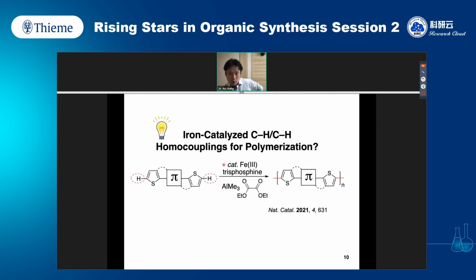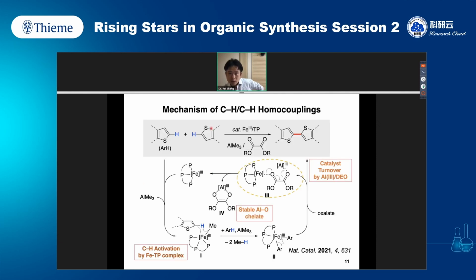In order to do the polycondensation, we need to understand the CH activation and dimerization reaction very well. Here I show the working mechanism. The abundant metals, iron and aluminum, both very cheap, cooperate together. We can see from the scheme that the first step is a twofold CH activation at the thiophene C2 position with the iron tridentate phosphine complex. We use trimethyl aluminum as a base to deprotonate the CH bond. Then reductive elimination gives the bithiophene, which is very easy.